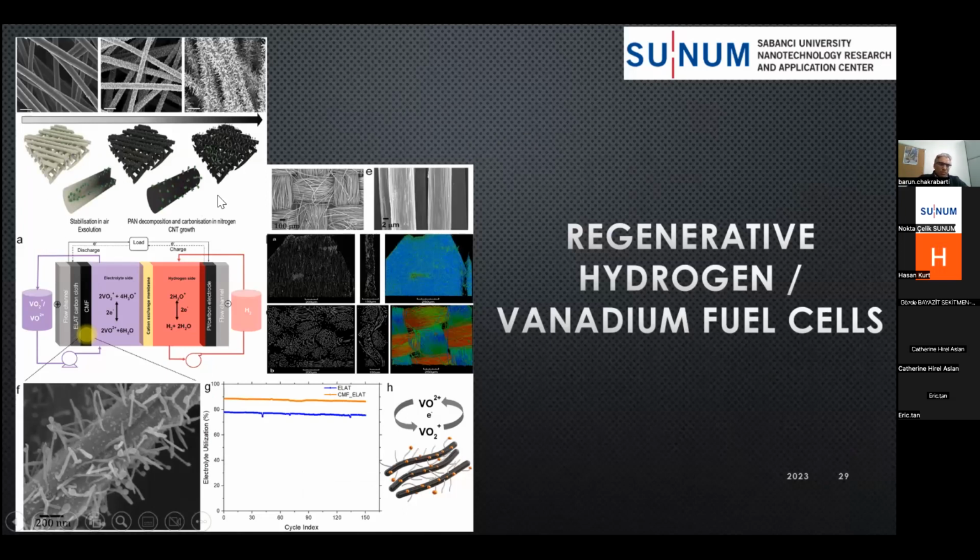This here shows the procedure in time, how using polyacrylonitrile and iron, like 30 to 48% of iron compared to the PAN, and then after that carbonization, you can see how the carbonized structures form, the hairy, trichome-like structures form after carbonization. This is a SEM of a commercially available carbon cloth electrode, which has been reported to do very well in the flow battery literature by a flow battery group at MIT. So we were collaborating with MIT in the 2020s, like 3 years ago, and they suggested we use this particular electrode and test that in our systems.